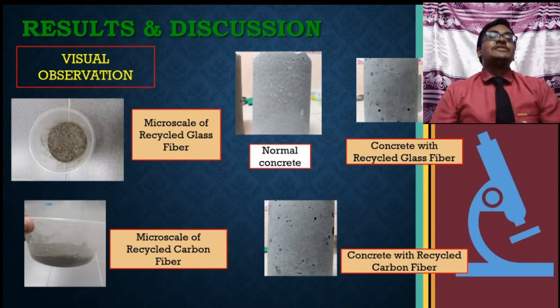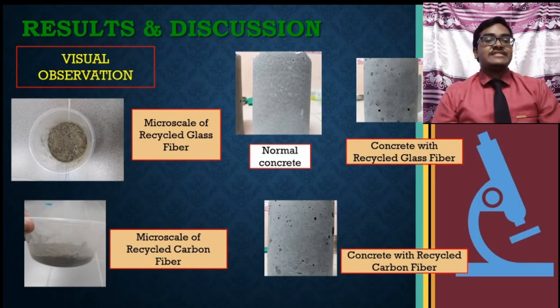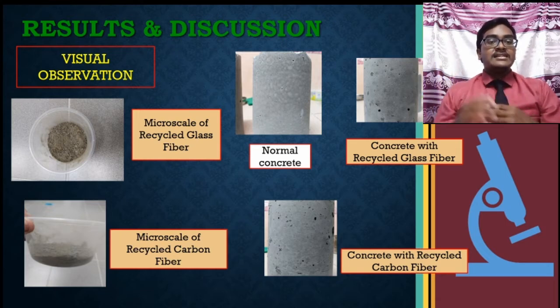Okay, now I'm going to explain results and discussion. First of all, visual observation. As shown in the figure, the recycled glass fiber and recycled carbon fiber are in microscale size after the grinding process. Besides, after the grinding process, the recycled glass fiber and recycled carbon fiber in microscale size were mixed together with water, cement and sand to make the concrete.